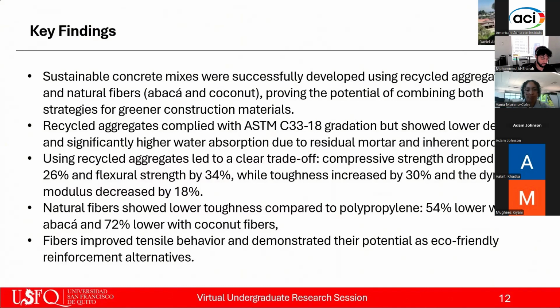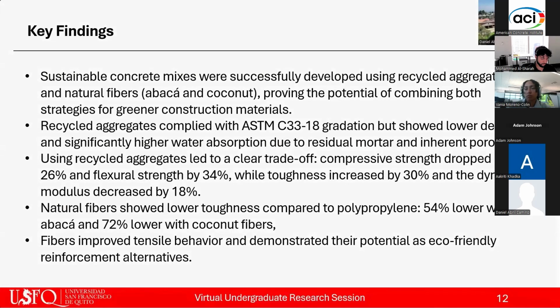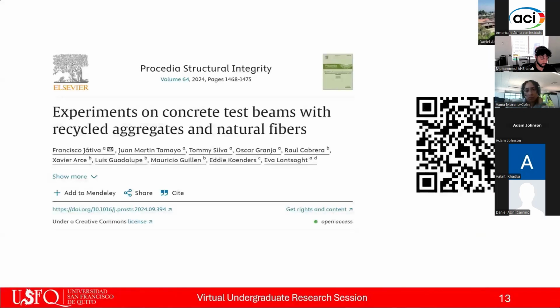Compared to polypropylene, natural fibers absorbed less energy, about half with abacá and less than 1/3 with coconut. But at a 4% dosage, abacá achieved the highest tensile strength among all natural fibers. Polypropylene at 4% offered the greatest deformation capacity, while all fiber reinforced mixes surpassed the tensile strength of plain cement paste. Part of this work was published in a scientific article developed by the Universidad San Francisco de Quito.